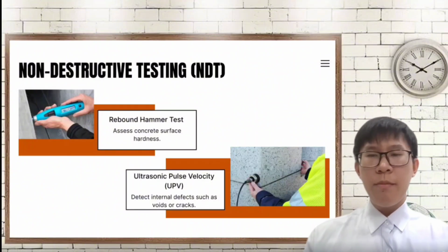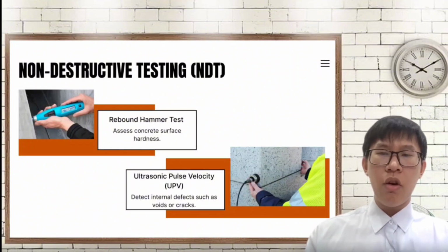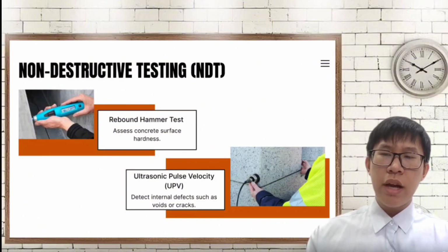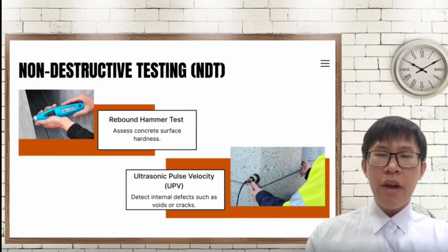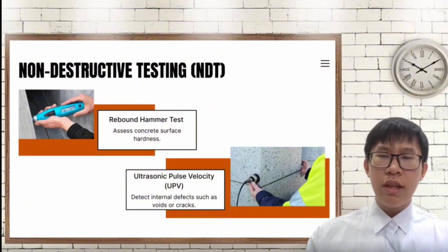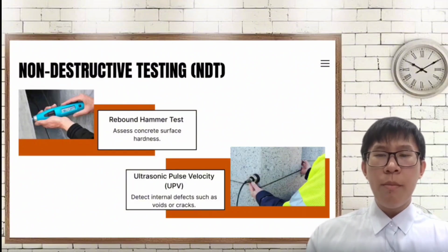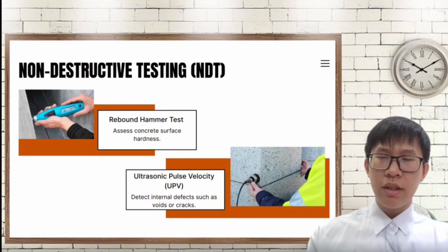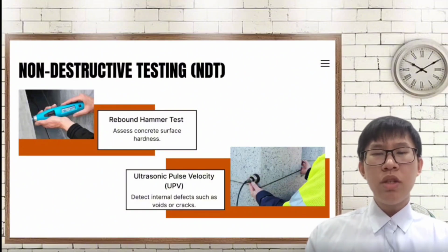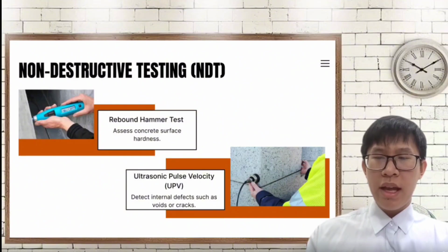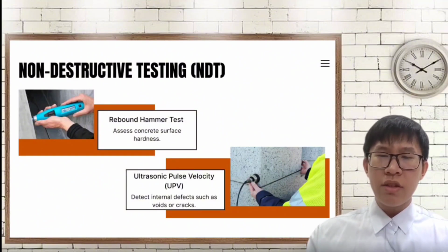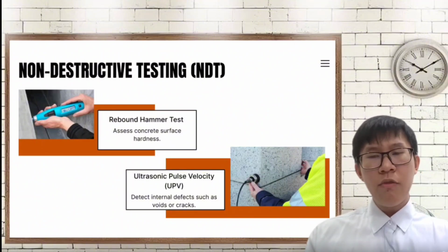Lastly, we have implemented non-destructive testing or NDT to safely analyze the inner condition of the structural elements. We use the rebound hammer test to quickly assess the concrete surface hardness across different locations. These were combined with ultrasonic pulse velocity (UPV) testing, which allowed us to map out and detect any deep internal defects such as voids or hidden cracks inside the concrete. That's all from my part.